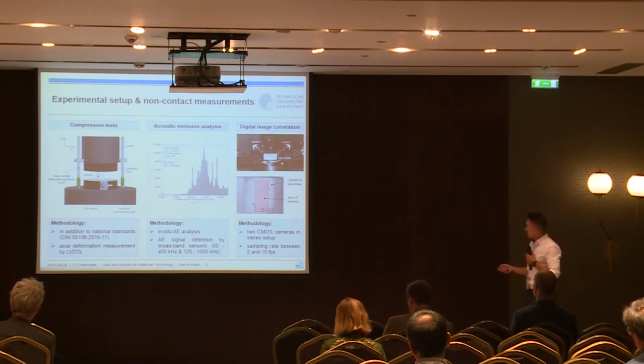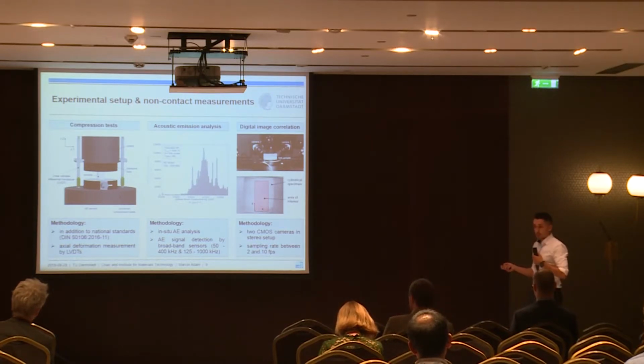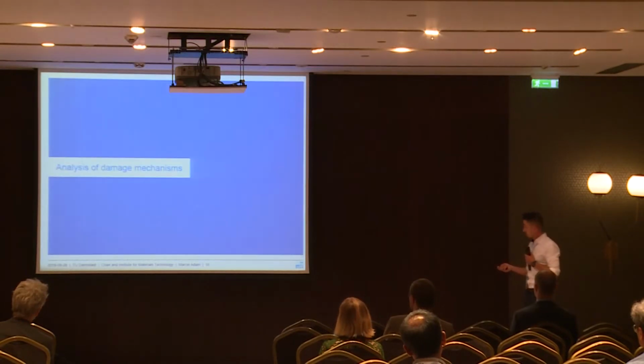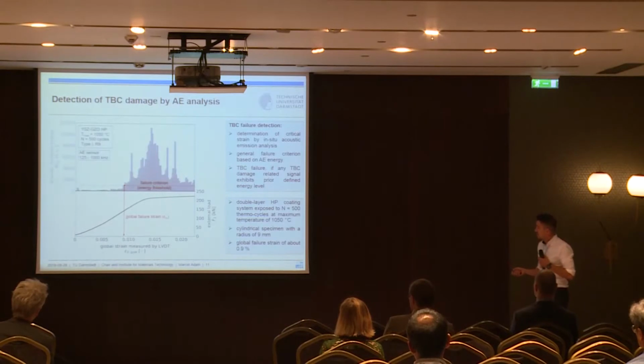In addition to that, we also used a stereo camera setup. We had two CMOS cameras in stereo setup, oriented at an angle of 25 degrees to each other, to look at the two-dimensional surface strain field on a curved TBC surface. With this stereo camera setup, we also get information about the radial or out-of-plane deformation of our cylindrical samples. So let's have a look at the results we got from the acoustic emission analysis.